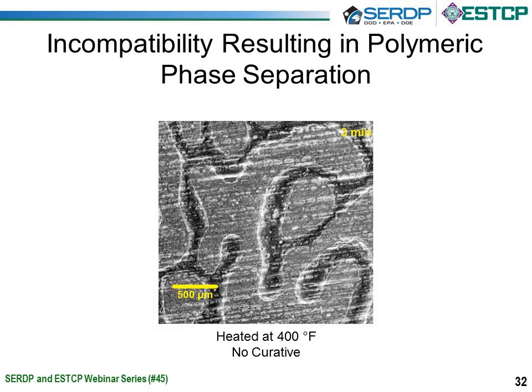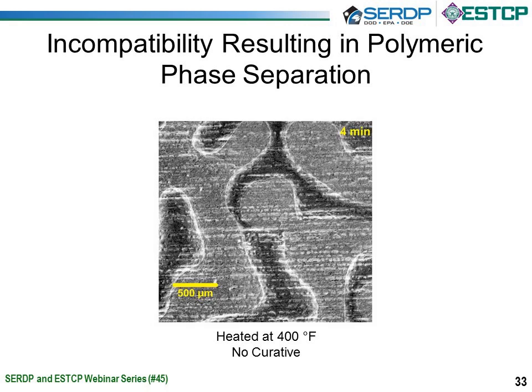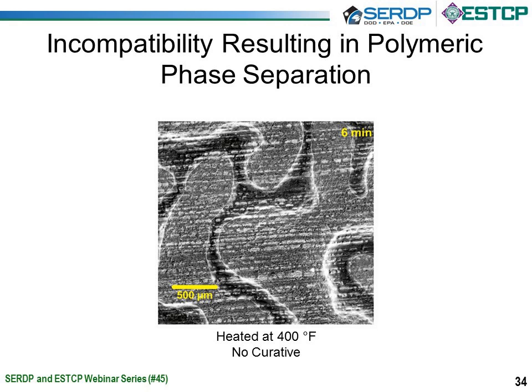We see this process continue to flow and level with increased phase separation, and this continues throughout the heating process. In slide 32, you can see a greater degree of coalescence and this continued phase separation, as would be desired to achieve the goals that Mark alluded to earlier. In slide 33, at 4 minutes, you can see the phase separation continues. Notice that at no point are we achieving complete stratification, which is very desirable, and we feel that's probably an interaction between the polyol and the aluminum substrate. And finally, at slide 34 is when I stop. We continue to coalesce without the hindrance of stratification.